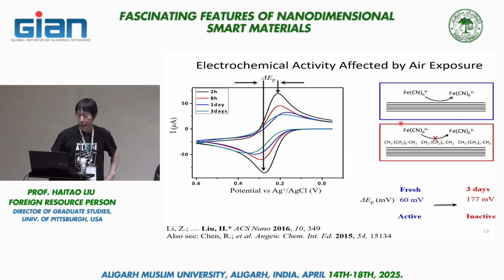Now, how do I understand this? It becomes pretty obvious if you accept that the surface of the electrode is not clean after a couple of days. If you have a clean surface with no hydrocarbon, then the electron transfer goes directly from the graphite electrode to the solution redox couple. However, if you have a layer of oil, essentially hydrocarbon, which is not conductive, then the electron transfer has to go through this additional layer. This is electron tunneling, essentially, and electron tunneling is exponentially sensitive to the distance you have to go through. So the hypothesis here is that interfacial contamination would reduce the electrochemical activity of basal plane graphite.